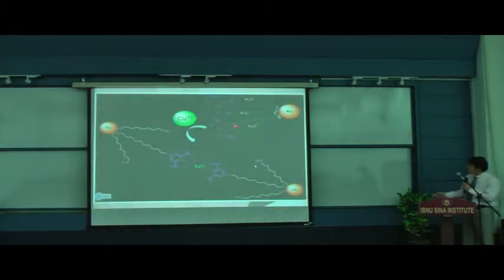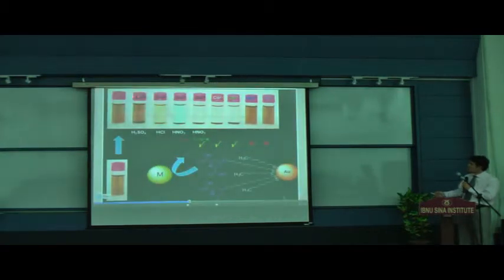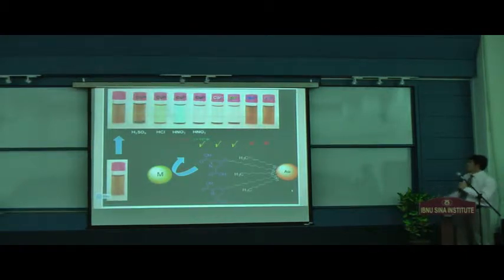Also, as I mentioned earlier, we played with the tail group and we made this 3D dicarboxylic acid. I forgot the name of this molecule. And it was also colorimetric sensor to detect copper, Cu2+ cation. Also, it was selective over the cobalt, zinc, lithium, and lead. So, optical, or let's say colorimetric sensor, work based on the surface plasmon resonance of gold nanoparticle.